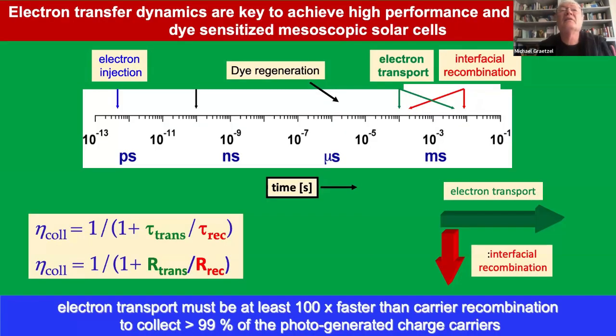Yeah, and so we understood that phenomenon by doing a lot of fundamental studies. And at the end, I mean, the physicists first were very skeptical. They agreed that we could inject electrons in these particles, but the collection was a problem for them. So there was no field to separate positive, negative charges, and also the diffusion was very slow in these systems.